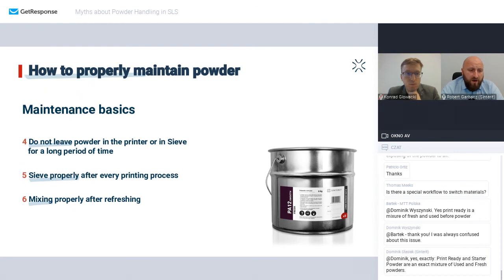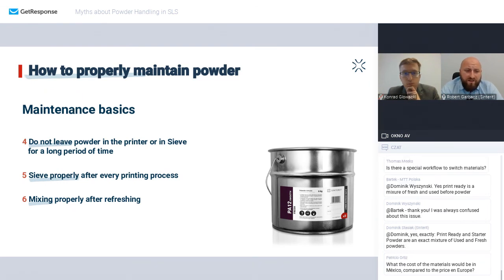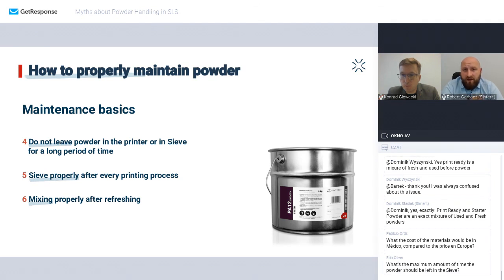And the fourth one is do not leave the powder in the printer or in the sieve for a long period of time. This is super important because usually you leave the powder in the sieve and go do some other things, and then you return to the sieve after 2-3 hours. This time is enough for the powder to take the humidity in. So imagine that you need to maintain all the rules and all the steps in the cycle as they are supposed to be. Do not leave any powder in these places, and then you will not expose the powder to humidity, so you will not risk the powder getting wet.